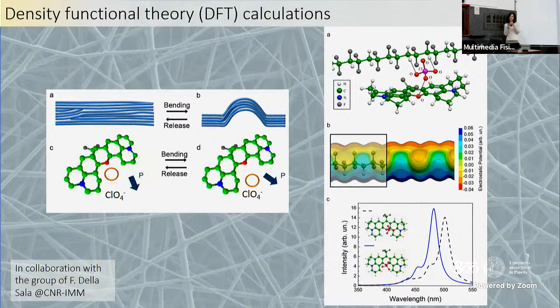a mechanophore state, so create states with different energy surfaces. And according to the interdistance, you can drive the material to different energy surface states, which correspond to different emission wavelengths. So finally, theoretically, one can tune the emission of the material up to 20 nanometers. And this is indeed very interesting. So the formation of this mechanophore state at the molecular level.